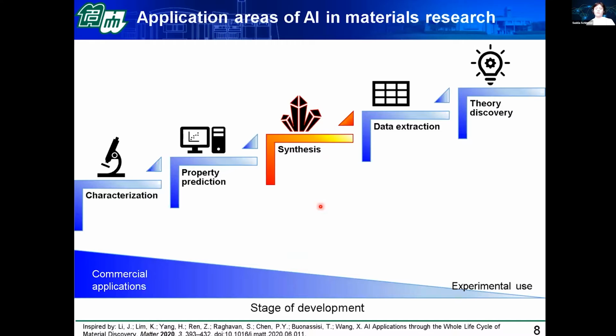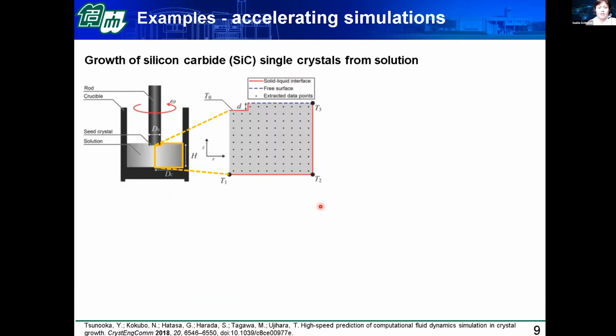Now I would like to talk about some examples from the field of synthesis, or in this case, crystal growth, where I have some more insight. The example here is taken from top-seeded solution growth of silicon carbide. So you can see the experimental setup used for this growth technique here, with the seed crystal and the solution. And in this first step, the authors used machine learning for accelerating numerical simulations.